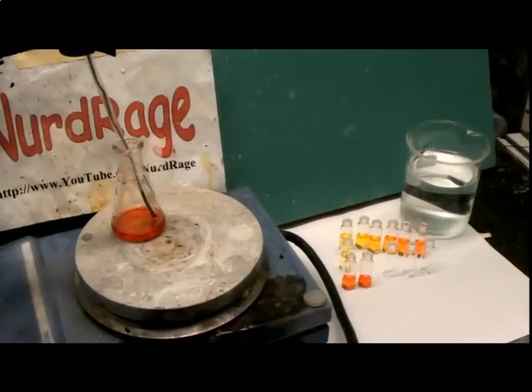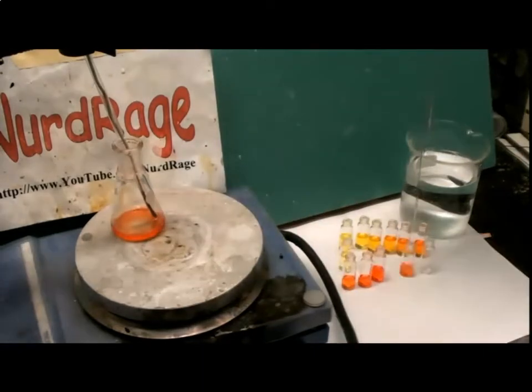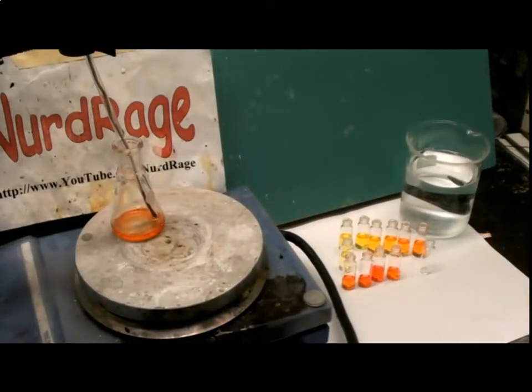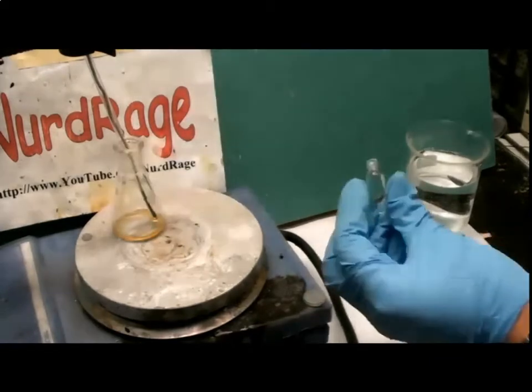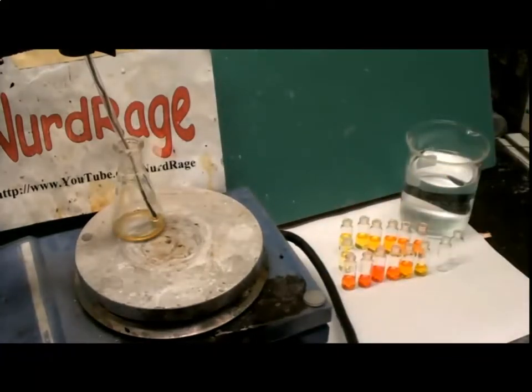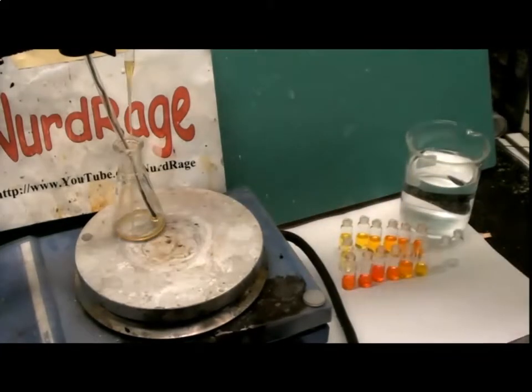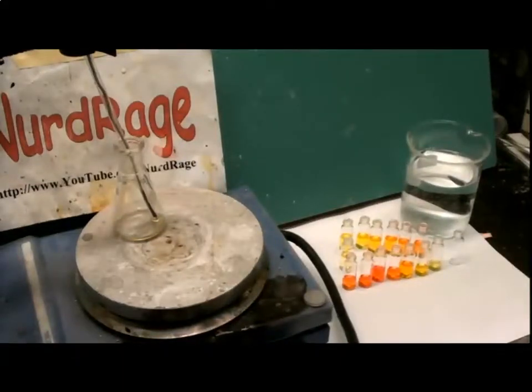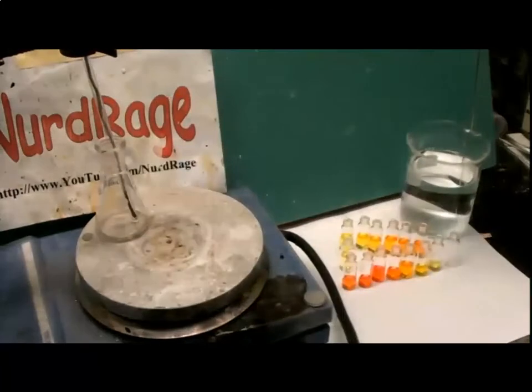What's happening is the cadmium oleate is reacting with the trioctylphosphine selenide to form cadmium selenide. These particles start small but grow in size as the solution reacts. Now this growth only continues if the temperature is maintained, so withdrawing it at regular intervals and placing it in a room temperature vial stops the reaction and locks the particles into their current size. So by controlling how long they stay in hot solution, we can control their size. The oleic acid surrounds or caps the particles and keeps them from aggregating.